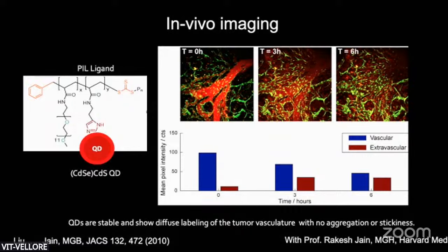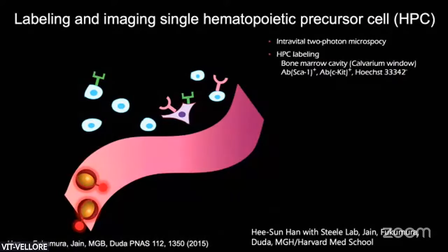We learned to coat the surface of these nanomaterials with what we might call biological Teflon, with PEG groups, and attach antibodies to them, for instance. This is a 3-color experiment with quantum dots of 2 different colors in a mouse model, to look for special, rare cells that are kind of like stem cells.